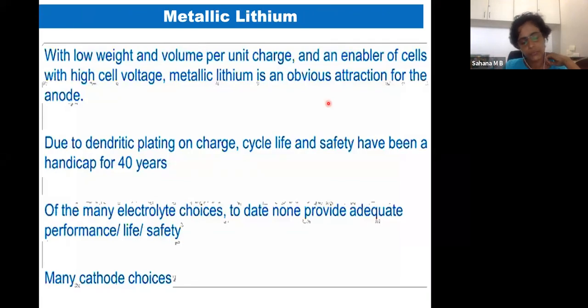Another advantage of going from liquid cells to the solid cell is, you may recall the band diagram, where with the redox potential of lithium metal, you get a higher voltage of the cell, whereas with lithium ion, where we use graphite, we get a lower voltage. So basically the energy density lowers when we use graphite instead of lithium metal. But why we cannot use lithium metal is, with liquid electrolyte, we have a lot of safety problems. Even with graphite, we have safety problems.